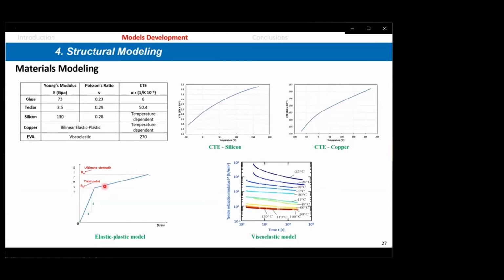And the copper is in fact elastic plastic, so it has linear elasticity. Then we get to the yield point, and then we have plasticity. So we considered linear elasticity with plasticity, with hardening, and this is kinematic hardening. For the EVA, which is a polymeric material, this is a viscoelastic material which is also highly dependent on temperature. We took a viscoelastic model which is temperature dependent, and that's what we input into our finite element simulations.